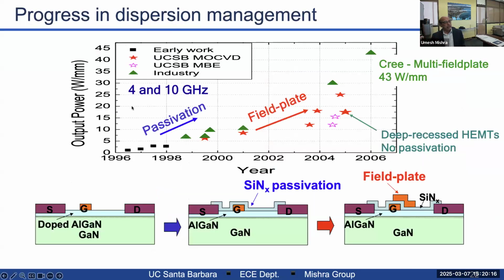So this is how we progressed in dispersion management. First, in the beginning, we had doped AlGaN. Our first devices that we grew in Steve's lab and in his homemade machine were AlGaN GaN HEMTs, but we silicon doped the AlGaN. And that's the only way we could get devices to work in the beginning. From 1996 onwards, we got about 4 watts per millimeter, not bad in those days, with no passivation. Along came passivation, and then it jumped to 10 watts per millimeter. Then we introduced field plate technologies, and we went from 10 watts per millimeter to like 25 watts per millimeter. With multiple field plates, CREE in those days had 43 watts per millimeter.